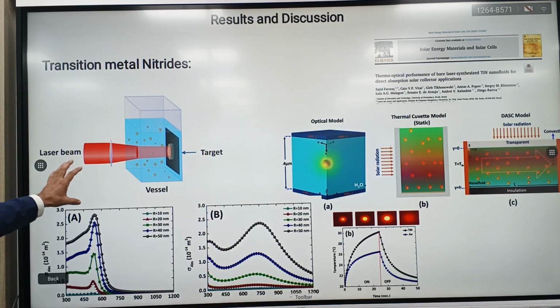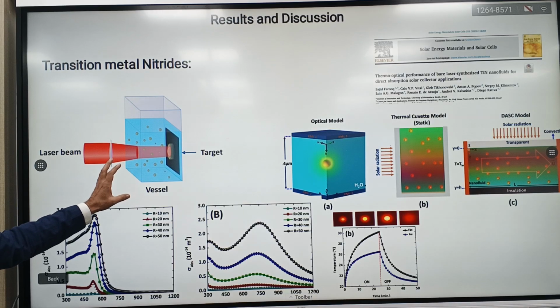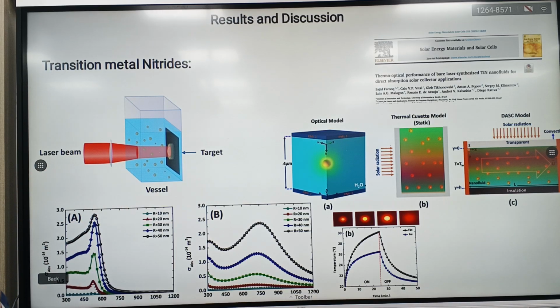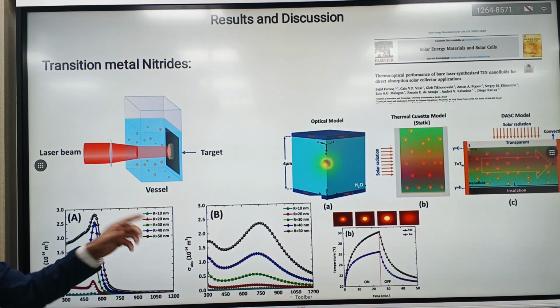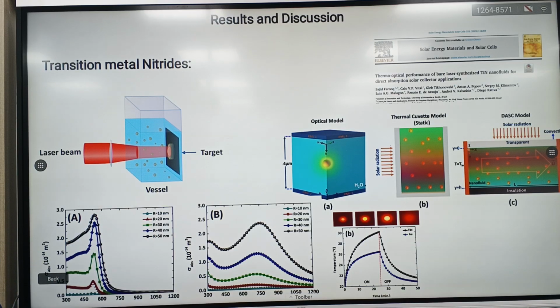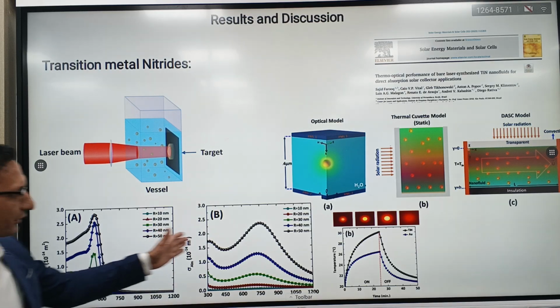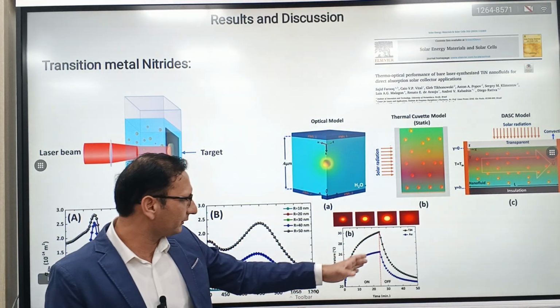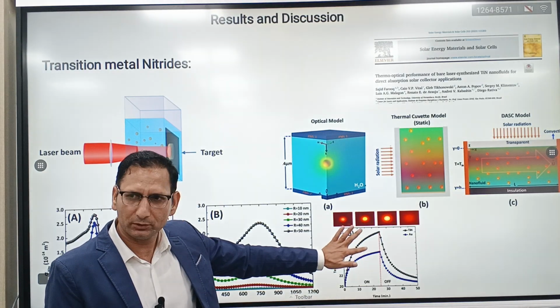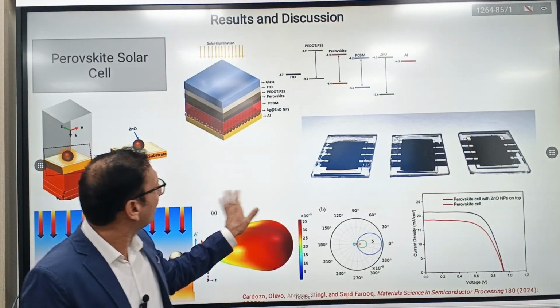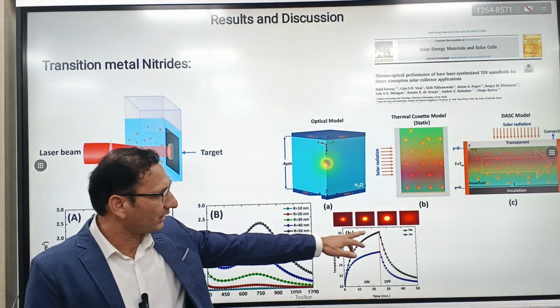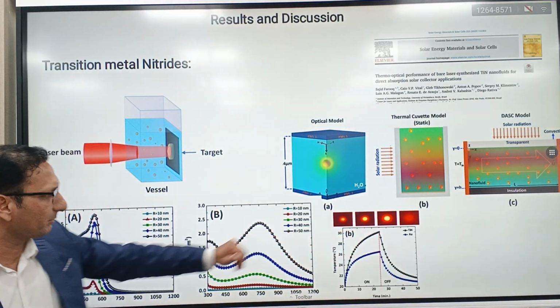So we prepare with laser ablation, and the zeta potential of the particles goes very negative, -40, -30, and you can keep them like 5 years. And this kind of particle is very useful for industrial application instead of gold or silver or other things. Because you have a broad spectrum, and this is experimental. You see the temperature variation between gold of the same size and titanium nitride.